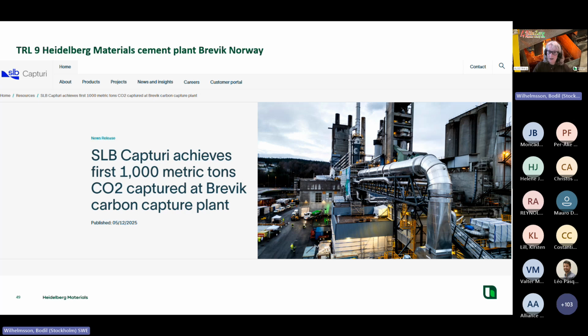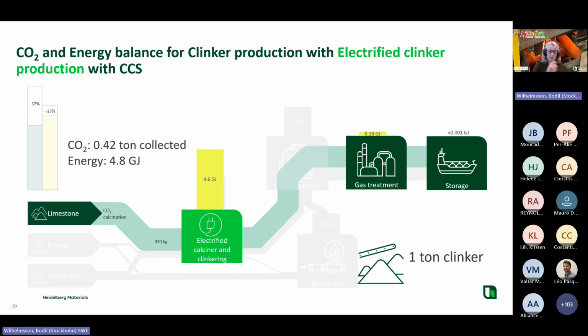But for the future, if you don't have waste heat from your plant, is there something else you can do? Of course, then we have to test: can we electrify the cement production? And to give you the advantage of electrifying the cement clinker production, I'd like to show you this picture. If you remember the two last ones, if we then electrify the production, so all the heating is done with some electrical source, it means that only the CO2 from the raw material needs to be collected. So from 0.67, we can decrease it to 0.42 ton per ton clinker produced, which is a 37% decrease.